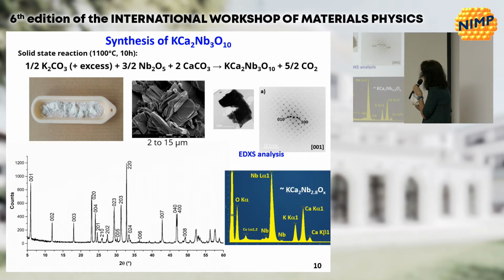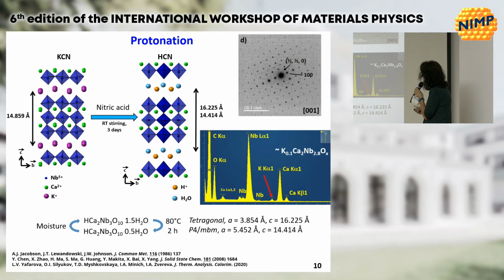We obtain this white powder, and by scanning electron microscopy, we can see that we have plates for the crystals of this powder, and then we check the crystallinity of the powder by the conventional structural and microstructural techniques. Then we have to exfoliate this material. This is a two-step process, a chemical process.